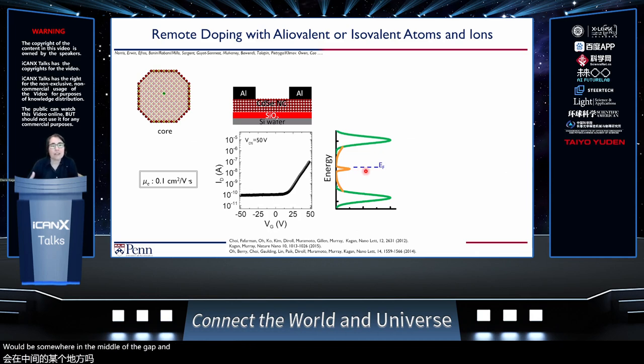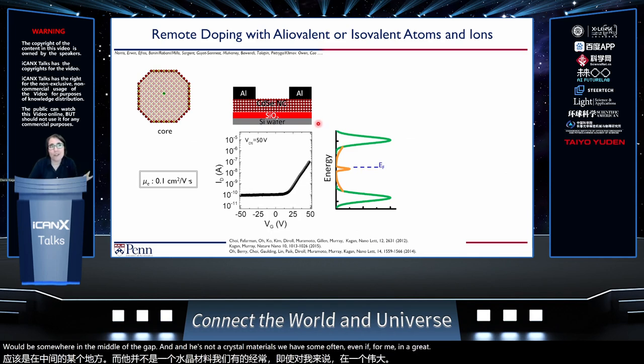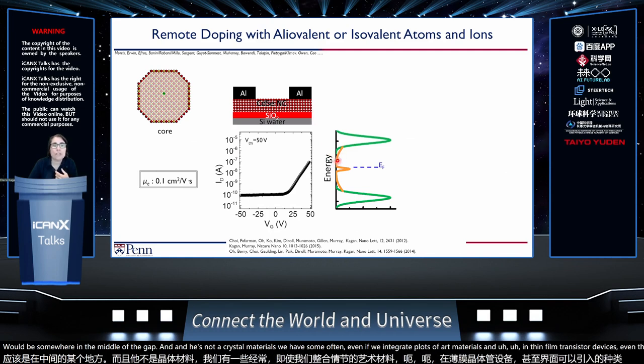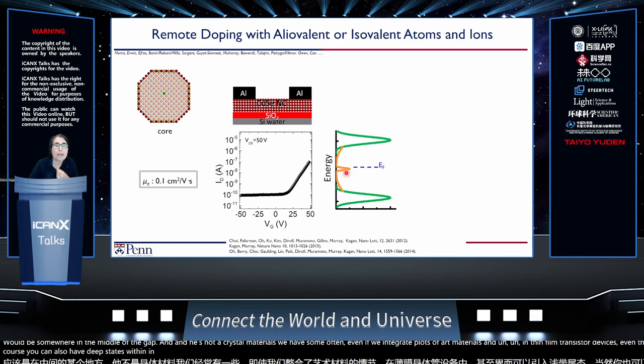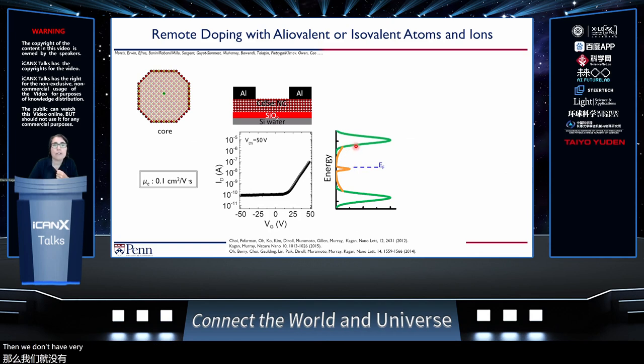And in these nanocrystalline materials, even when we integrate them in thin film transistor devices, even the interface can introduce shallow band tail states. And of course, you can also have deep states within the gap. As a result, if the Fermi level is here, then we don't have very many carriers in the high density electronic states up here where you'd expect to see good transport. And so if you characterize the mobility in these materials, you'd see something like 0.1 centimeter squared per volt second.